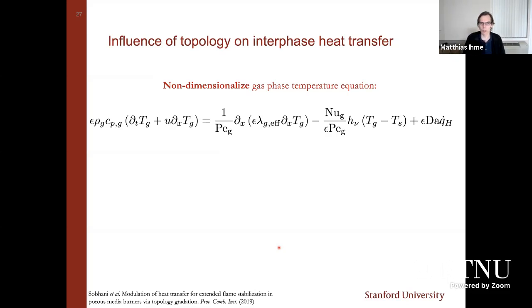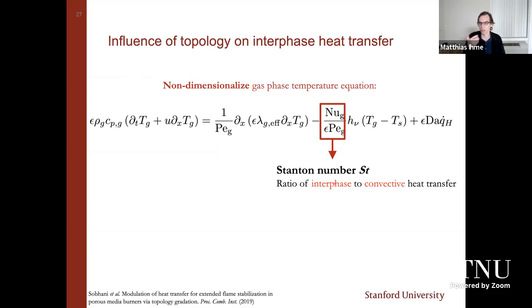Okay. Now, we can do some non-dimensionalizations, and this is really the motivation for this design that we are utilizing. If you normalize all of the governing equations, you're essentially identifying a ratio comparing the Nusselt number to the Peclet number. And I'm sure that many of you can remember that this is nothing else than the Stanton number, the ratio of the interface to convective heat transfer. This is the heat exchange between the solid and the gas phase to the convection. And what we like to do is we like to operate and tailor the system, as this is the key parameter to control the heat exchange between the solid.